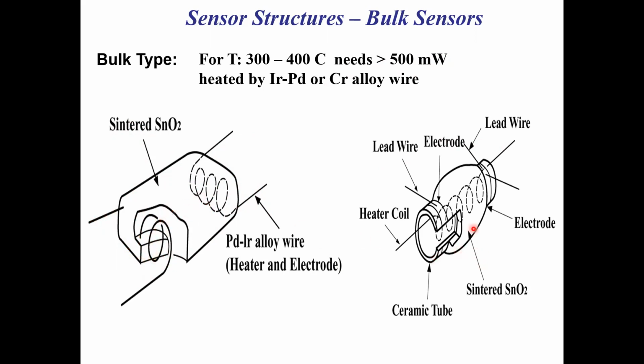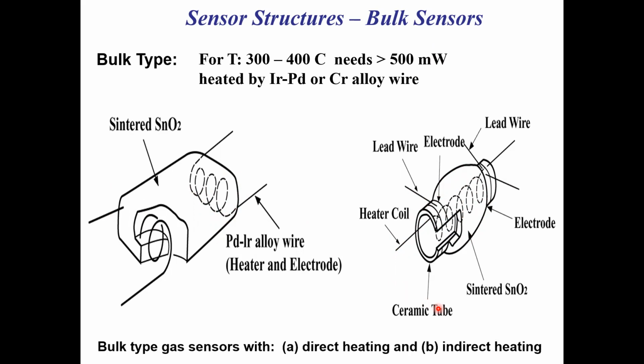Or you can make a sintered tin dioxide which is hollow and can be heated by radiation heat from, again, an electrical coil. Obviously, the power requirement here would be lower than in the previous case. But nonetheless, this will require hundreds of milliwatts of power. So what is desirable is that you make the sensor and minimize the mass by using thick film technology or screen printed technology, where the power requirement can be less than 200 milliwatt.